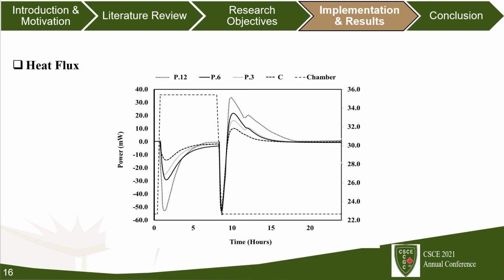Finally, we got a very interesting point in our research by measuring the heat flux for our samples. At age 28, the temperature of the chamber was maintained at 35 degrees for 9 hours. Then it was cooled down to ambient temperature, around 23 degrees. As you can see in this figure, generally, increasing the percentage of phase change material significantly increased the heat capacity and the mortar heat flux.